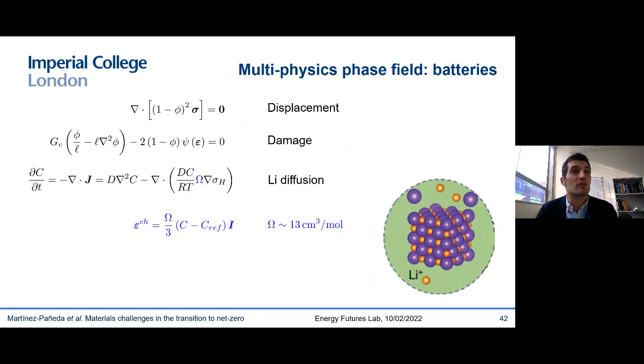And when you look at the equations describing the physics of this problem, you see that they actually have many similarities with the hydrogen case. You are essentially solving a coupled deformation diffusion fracture problem. And the main difference is that the partial molar volume is one order of magnitude larger than in the case of hydrogen. So we have chemical strains that result from this lithium intercalation.